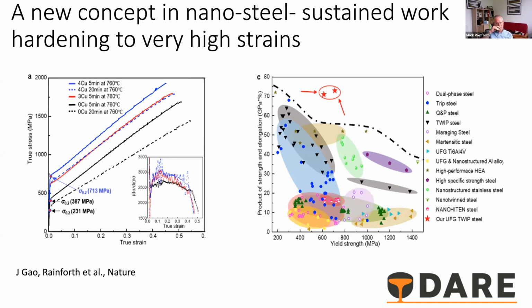But you can see top right there, those are all the steels, the wide range of high strength steels plotted. On the vertical axis, we've got the product of the strength and elongation, and on the bottom axis we've got the yield strength. And generally, you can see that this relatively straightforward iron, manganese, copper steel achieves far superior properties to the others.